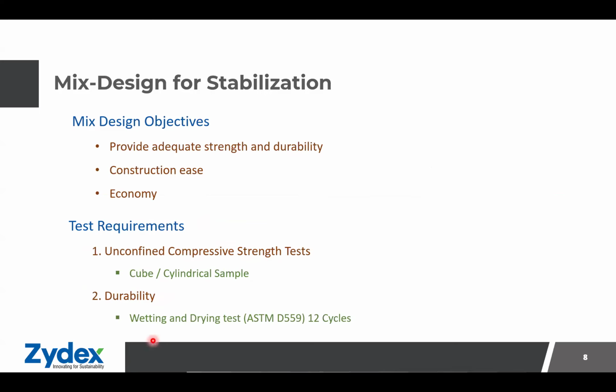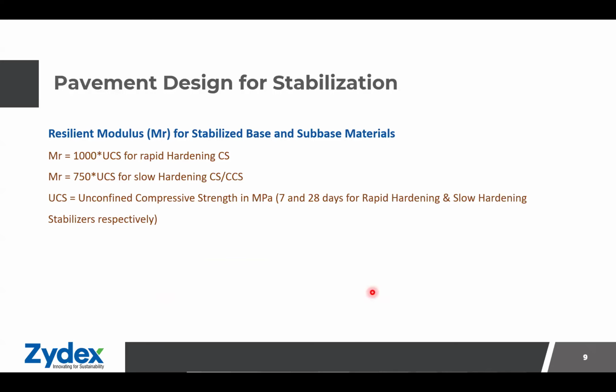In this, we have the drying and wetting cycles, 12 cycles we do, and then measure the amount of mass loss after each cycle. And also we report the UCS under dry, and the ratio of wet to dry UCS as a residual UCS. Now, talking about the pavement design, the most important parameter for the pavement design includes the resilient modulus.